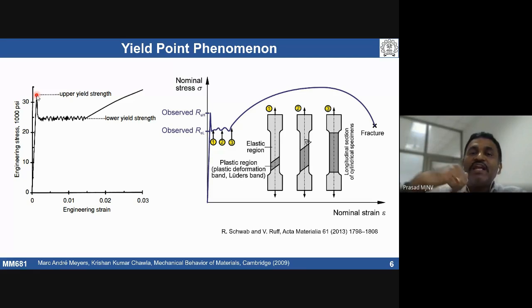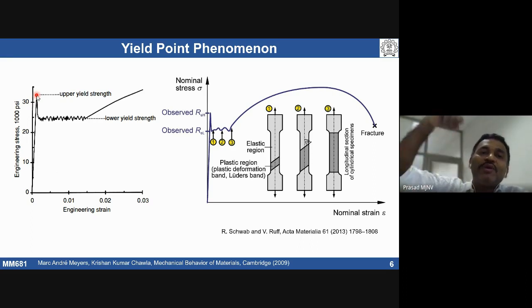That means your external strain rate is fixed, constant, but internal strain rate has gone up. So what happened? In order to maintain a balance, the material has to deform at the same rate as the external rate. In that case, your strain rate should come down to equal the strain rate you are applying externally.